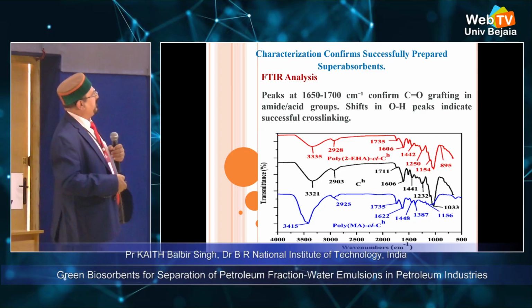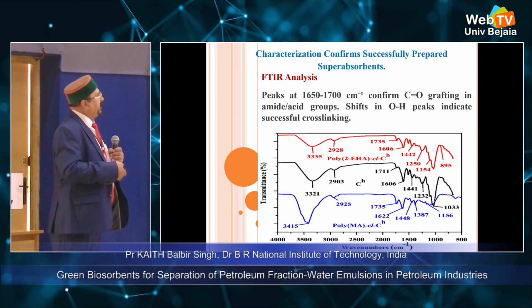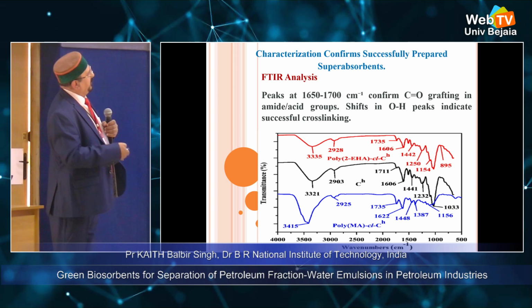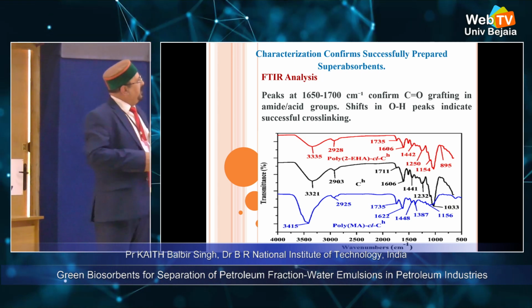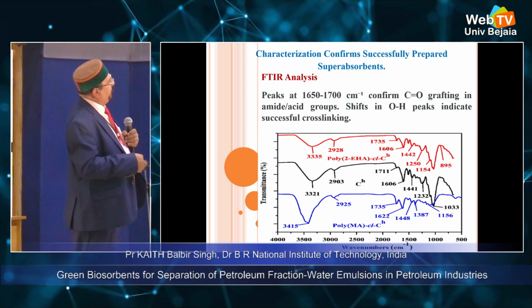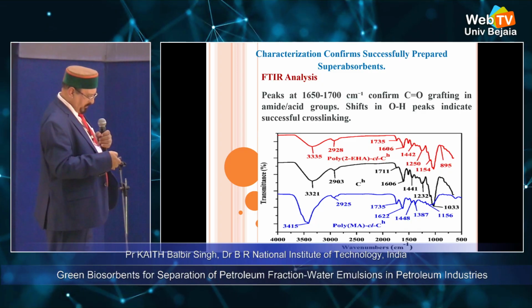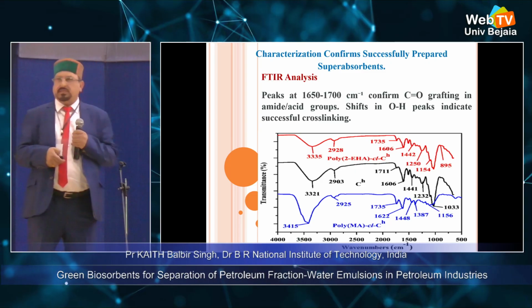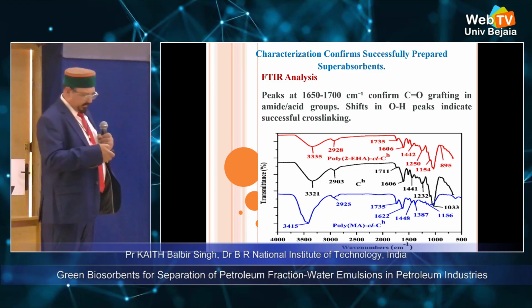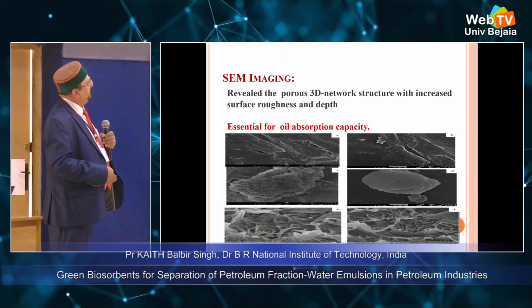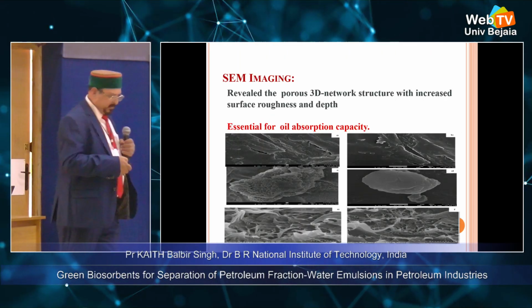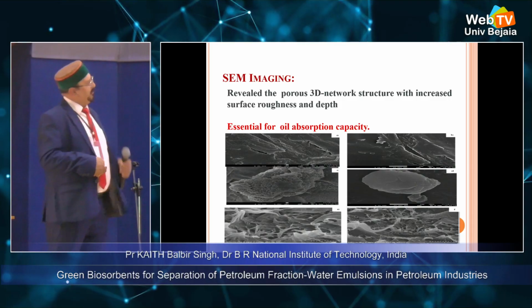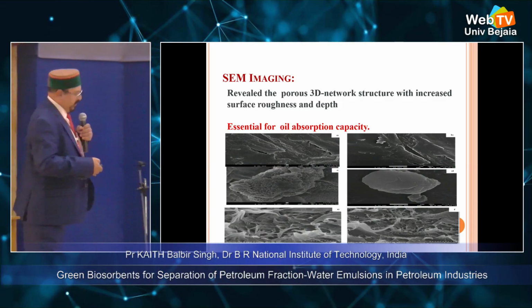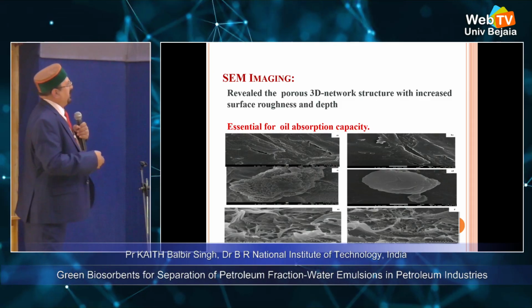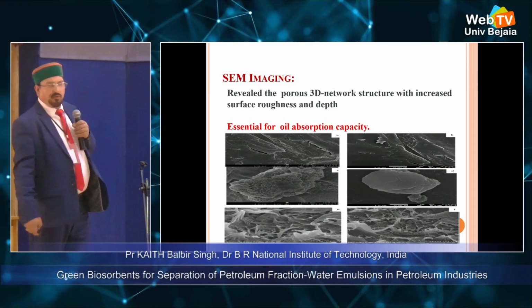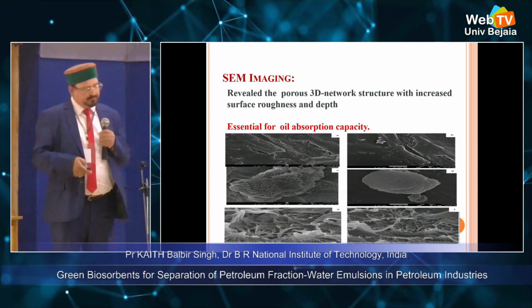And characterization was carried out, and you will find the shift in the peak for the CO group and COH group, and OH shift was observed, which clearly shows that grafting was there over the backbone. And we also did some images, and some images clearly showed the porosity of the materials, which is essential for the oil absorption capacity of the materials.